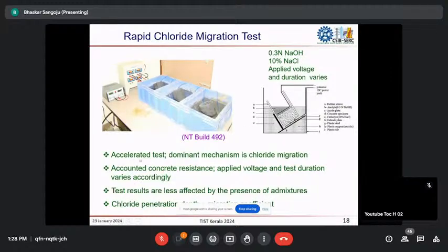And so here the concrete resistance is being accounted for. Therefore the applied voltage and test duration will be adjusted accordingly. And therefore the test results are less affected by the presence of admixtures. And also here what we are doing, no? We are not simply measuring the charge passed. Once the test duration is over, we take out this specimen, we break the specimen and we measure the chloride penetration depth alone. So this is more realistic when compared to the RCPT.